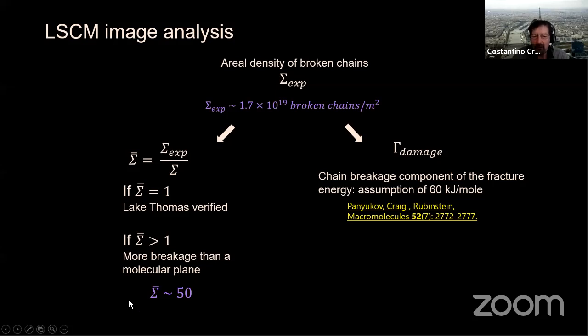Now, this is an experimental measurement. So this sigma bar is something we get directly from the fluorescence. If we want to go from that number to an energy, then we need to assume some value for the average energy to break one of these chains. Now, in the original Lake and Thomas model, this value of 350 kilojoules per mole, which is the energy of a carbon-carbon bond, is definitely an overestimate. The probability of breaking becomes very significant at much lower levels of forces and energies.